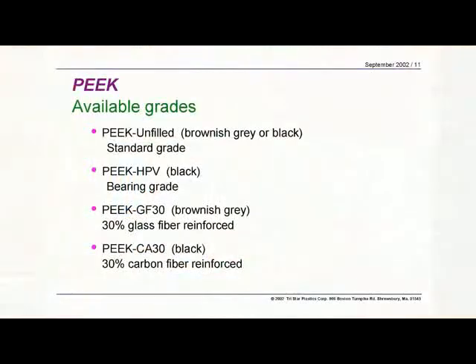The classic bearing grade PEEK is what's called HPV, or bearing grade 10-10-10, which is a combination of graphite powder, carbon fibers, and PTFE. So you have the additional strength of the carbon fibers, and then you have 2 essentially migratory lubricants in the graphite and the PTFE. And then finally we have glass-filled PEEK, and the glass-filleds are usually used for structural or sometimes for dielectric applications. Not so good for bearing applications because it tends to be a little abrasive, but still a very good material.